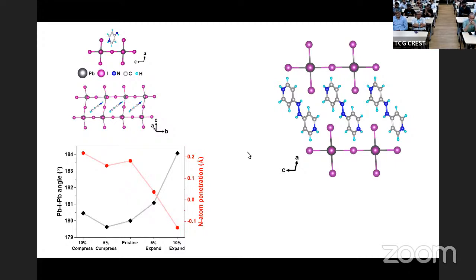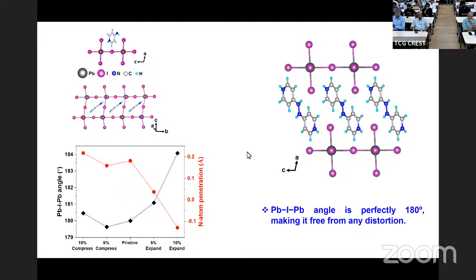As I approach the 180 degrees angle, or the c-axis gets a correct dimension, very quickly it's penetrating, but once it comes to the optimal geometry, it hardly penetrates anymore. Simply because now the electrostatic interaction between this head and the inorganic cage becomes too large, not allowing it to penetrate anymore. So if you stretch the c-axis further, all that it does is to tilt itself, retaining the penetration about the same, and that is reflected over here. And in order to accommodate this, up to this point, for it to get in, the Pb-I-Pb angle has to expand because the head is trying to get inside this cage defined by the iodine. So in order to accommodate this head sticking its nose in, the Pb-I-Pb angle becomes 180 degrees. And that is what we have realized.